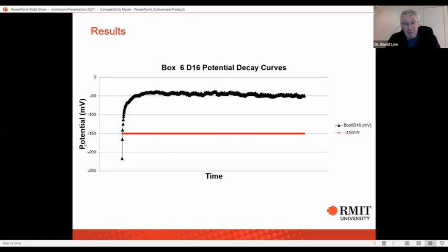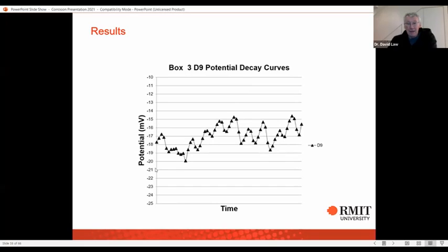So this would be the sort of thing that we would see. Here's our minus 150, and this was in the D9 beam. It goes up, and while it moves around a little bit over time, you can see it's still well above the minus 150, and there's no indication that it's starting to drift back down, no indication that corrosion is occurring. This is another one we looked at. You can see there are some ups and downs. These may be due to tidal action or environmental effects, but overall the potential is still drifting up, and it's very positive. So this would be very indicative that we do get residual protection in our structure.